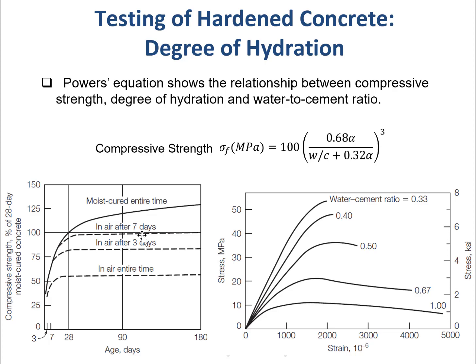So there is actually an equation to relate compressive strength, degree of hydration, and water to cement ratio. It's called Powers equation. It shows that the compressive strength equals 100 times (0.68 alpha over water to cement ratio plus 0.32 alpha) to the power of 3. Alpha is the degree of hydration.